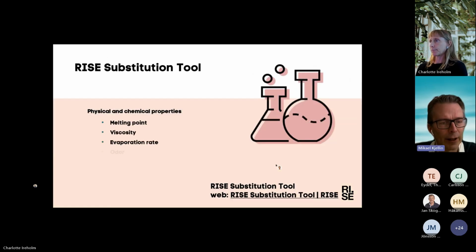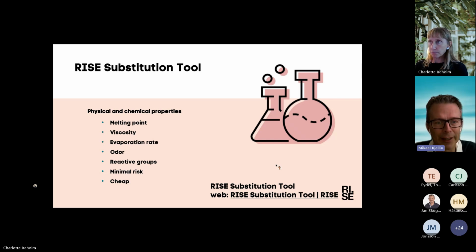So then you can rank solvents by solubilizing power, but there are many different aspects of the solvent that are important for whether you can use it. You have to consider the physical and chemical properties of the solvent, like, for example, melting point, viscosity, evaporation rate, and odor. And that's actually where the RISE substitution tool comes into play. From the Hansen program, you get a ranking of the solvents by solubilizing power. And then with the substitution tool, you filter with these physical and chemical properties. So you get fewer and fewer possible solvents, and then you can make an assessment of which solvent you can use. So next slide, please.